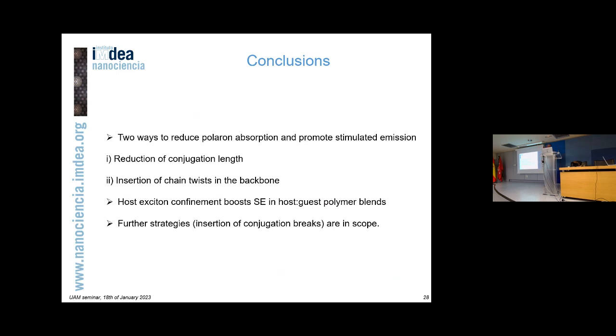So in a way, having a material with a high luminescence quantum yield is not enough to fulfill the requirements for a good laser material. This is probably one of the conclusions I want to draw, and this happens in polymers, but it can be extended to many others. You have to take into account other contributions, such as excited state absorption. And in these polymers in particular, the presence of charge transfer states, polarons, and even triplets can, in some cases, jeopardize this gain amplification process. So you need to find strategies to work around this.